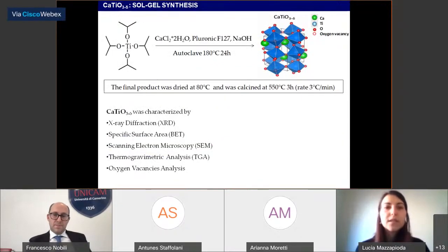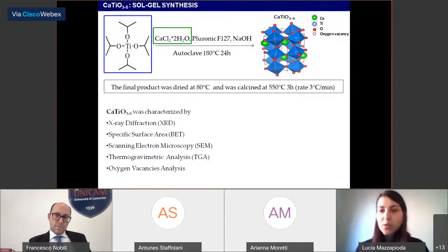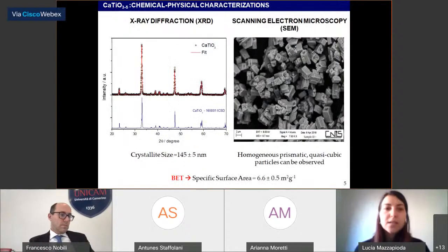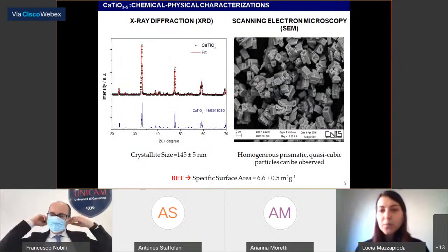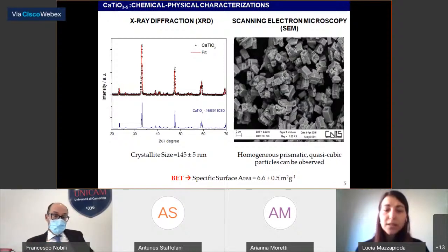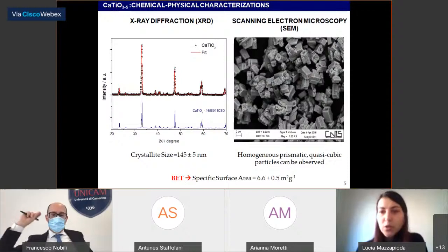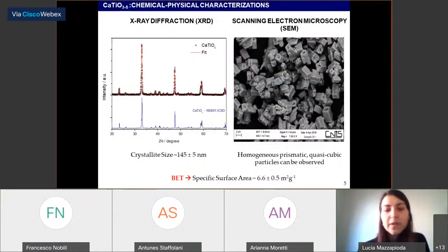The perovskite was synthesized by a sol-gel method using titanium isopropoxide and calcium chloride as precursors, and Pluronic F127 was used as a template and as a reducing agent in order to promote the formation of oxygen vacancies. The perovskite was characterized by XRD. The XRD pattern corresponds to an orthorhombic calcium titanate phase with an average crystallite size of 145 nanometers. The SEM image shows homogeneous prismatic particles with a specific surface area of about 6.6 square meters per gram.